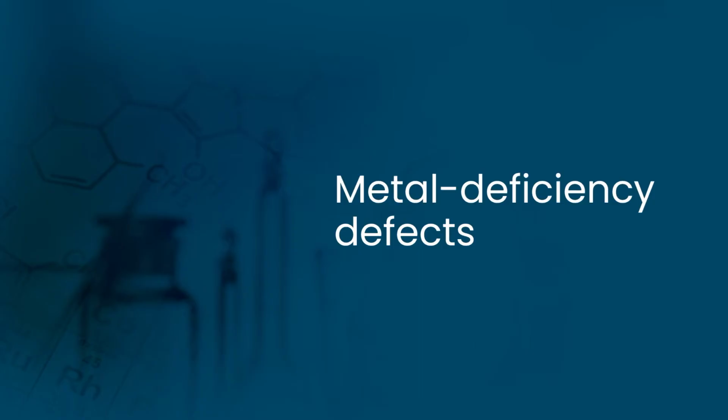Due to the presence of free electrons in lattice sites or interstitial sites, compounds containing metal excess defect show some electrical conductivity and act as n-type semiconductors. Second classification, metal deficiency defects or non-metal excess defect.